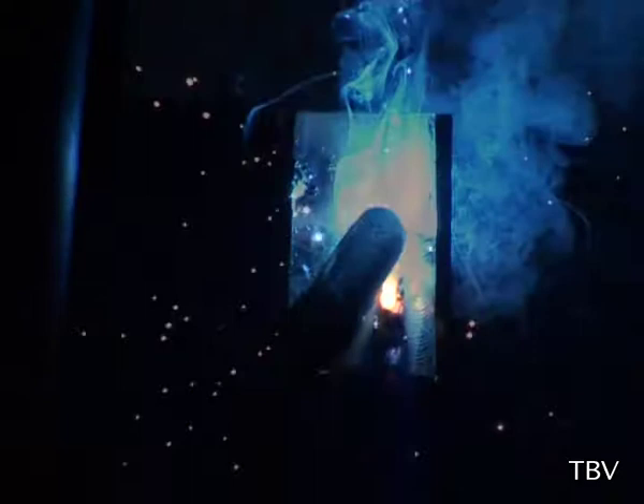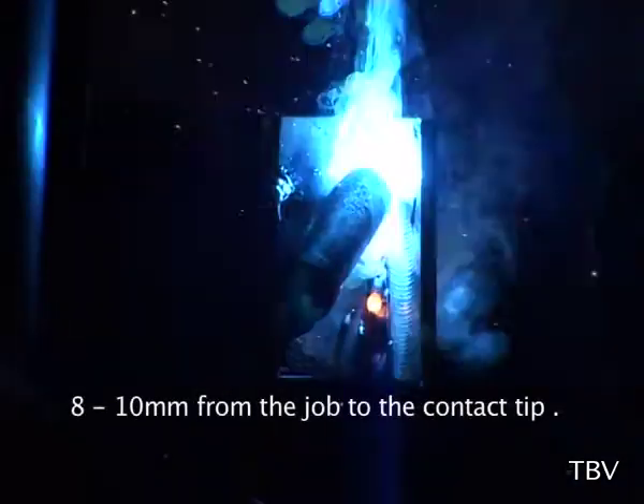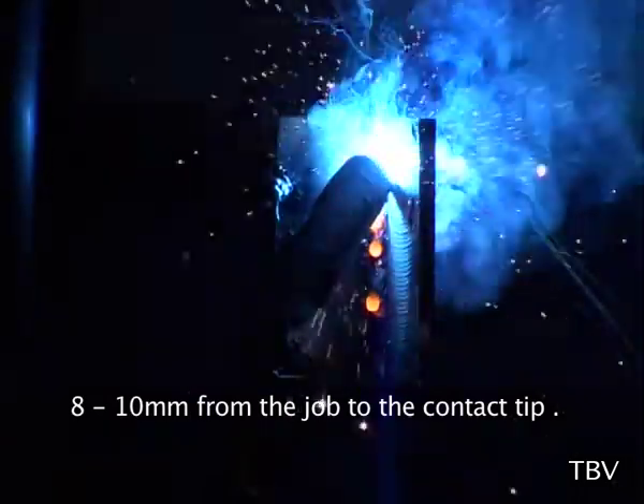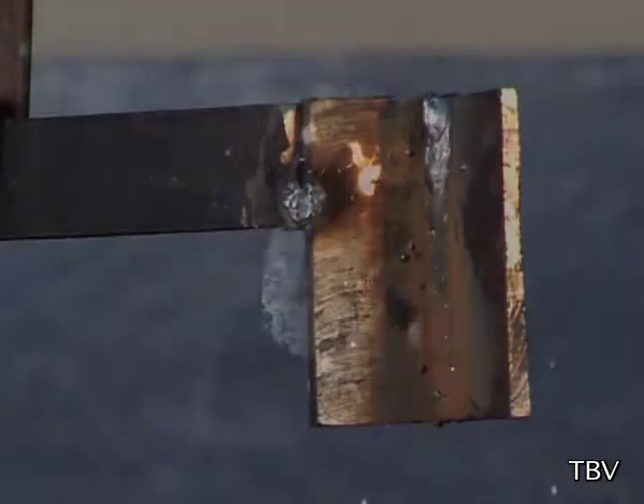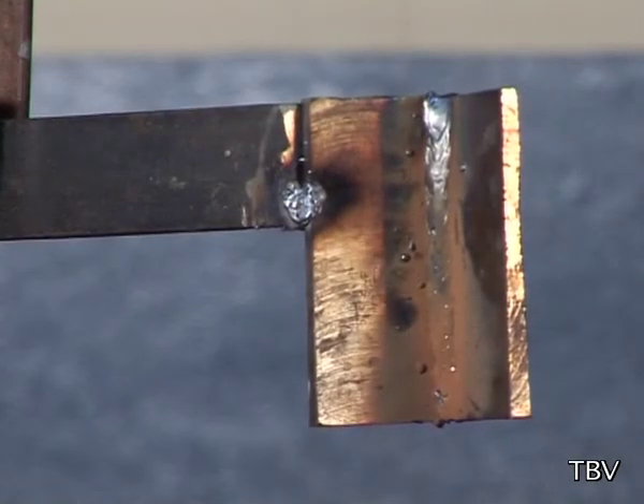Maintain the angle of the torch at 10 to 15 degrees towards the direction of travel throughout the weld length. Maintain the filler wire stick out. Deposit the bead on the joint of the job from one end to the other. Weld to the full length of the workpiece by filling the material in the weld area, moving upward in forward movement. Allow it to cool completely.